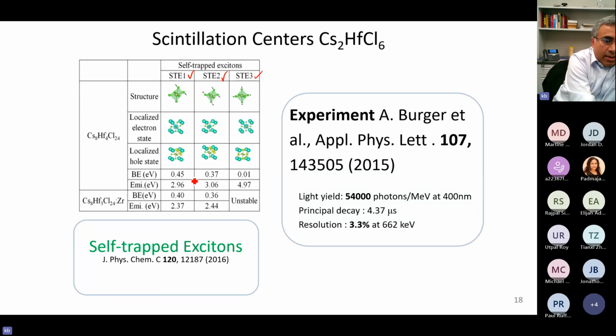We found that STE1 is the most stable, STE2 is next, and STE3 is not very stable. When we see these kinds of values, these are in electron volts, 0.01, if you take into account the accuracy of our calculations, we can say that STE3 is unlikely to be stable. Under thermal conditions, they will dissociate. But STE1 and STE2 have enough binding energy to stay stable even under normal conditions.